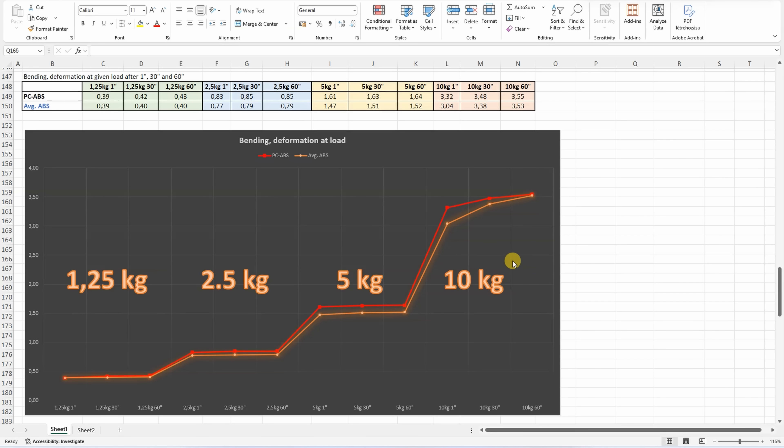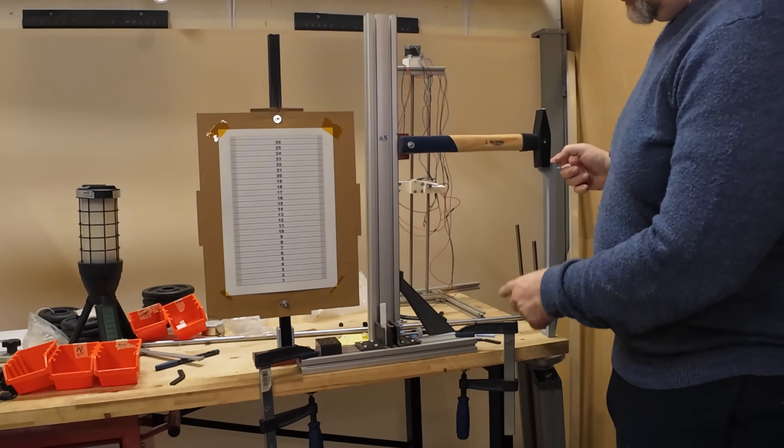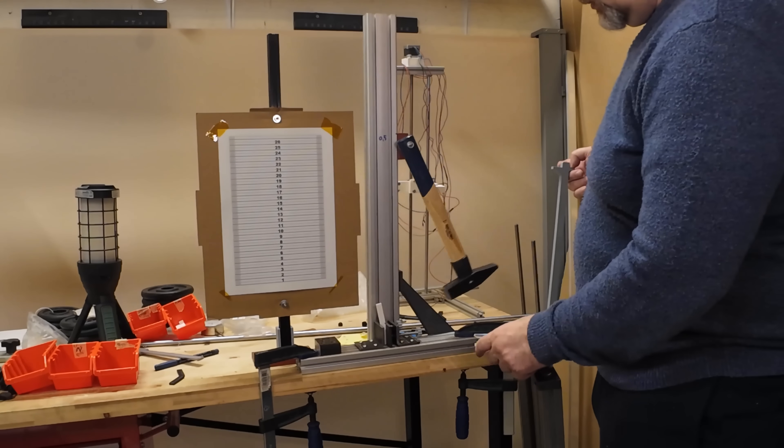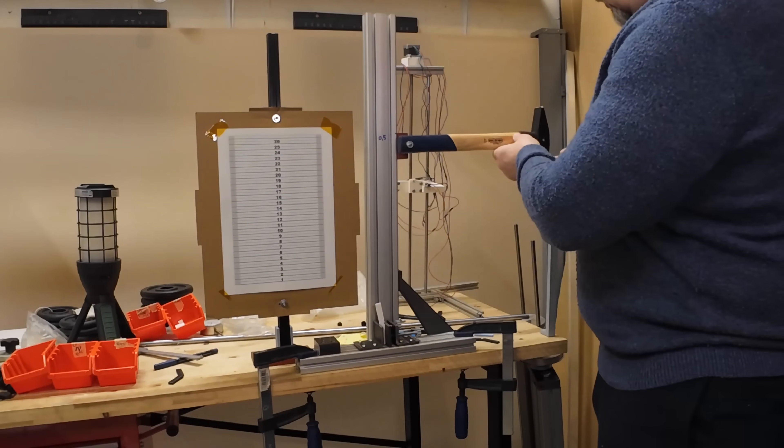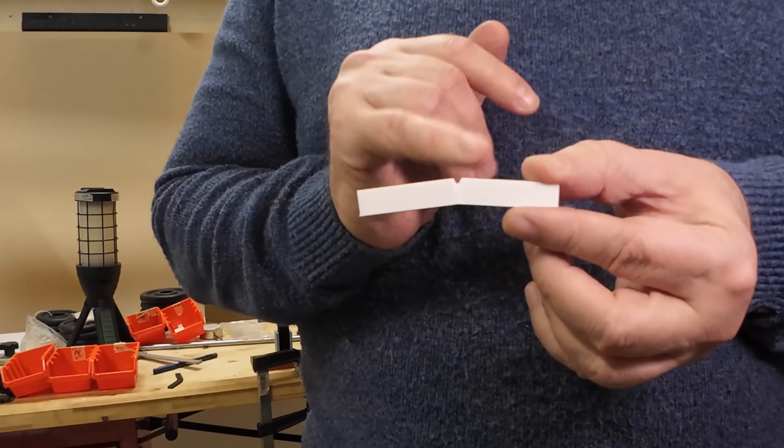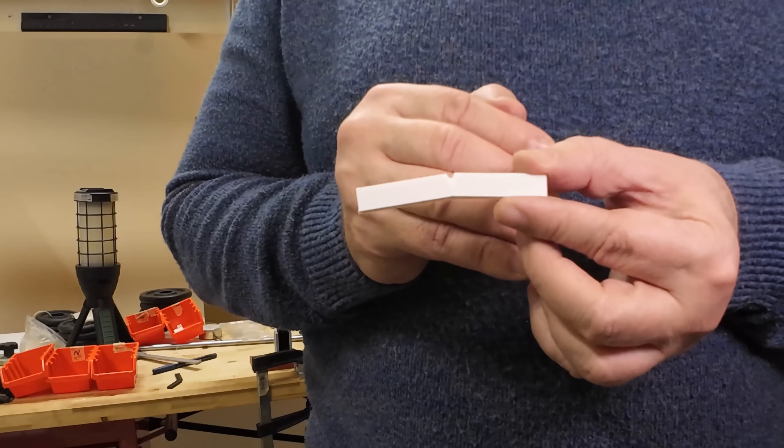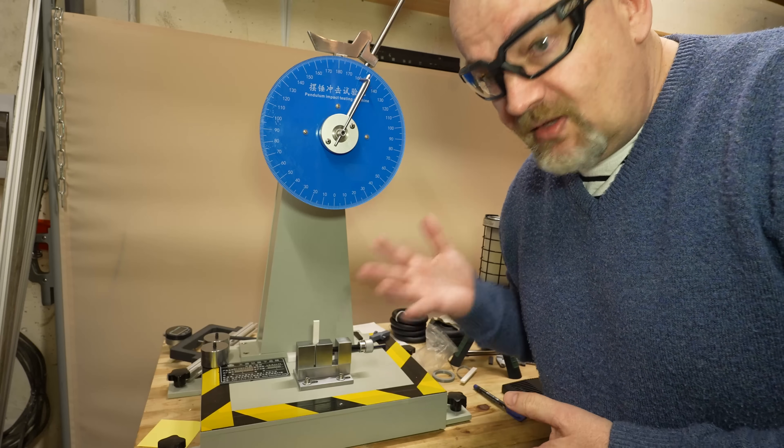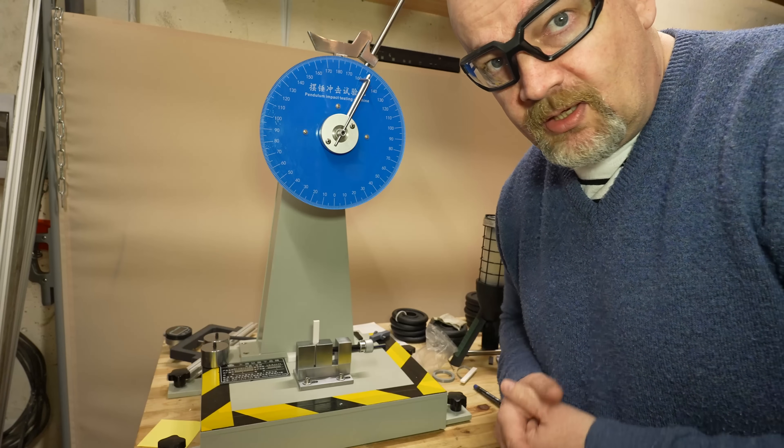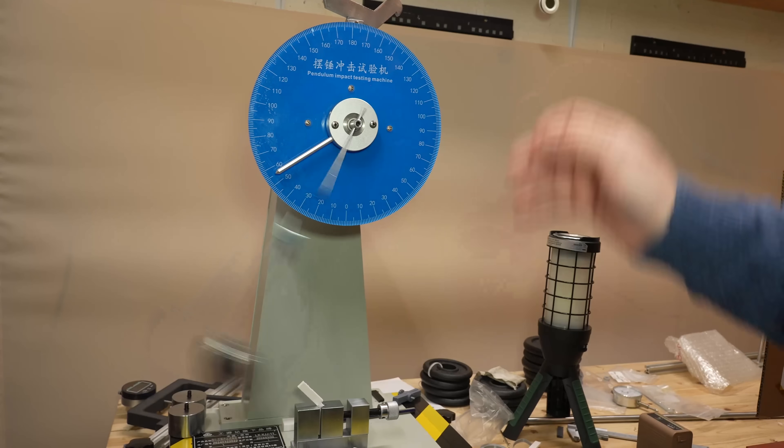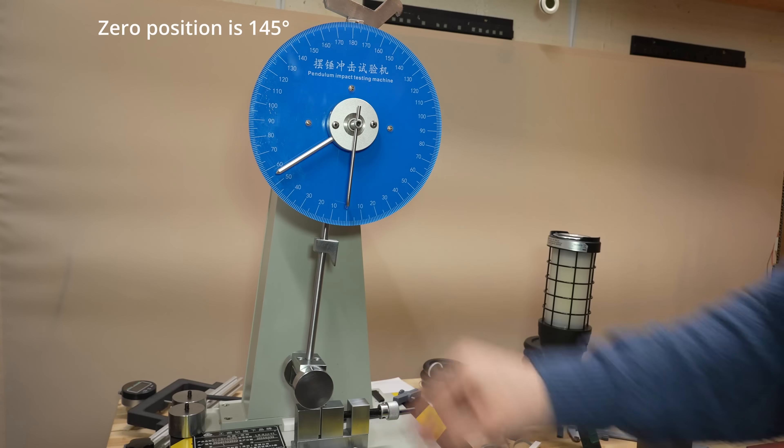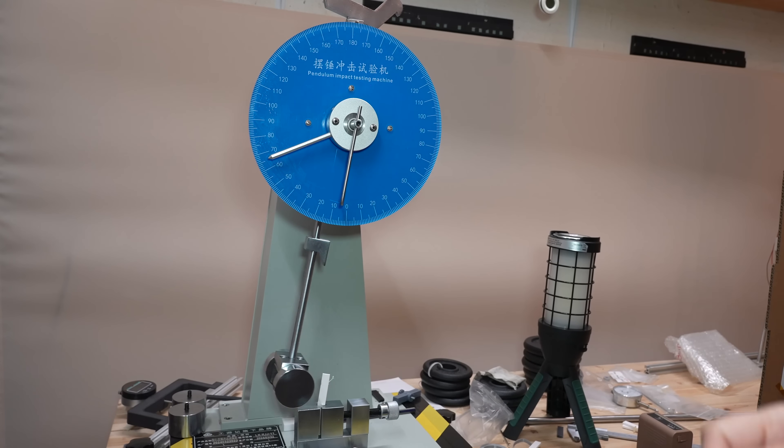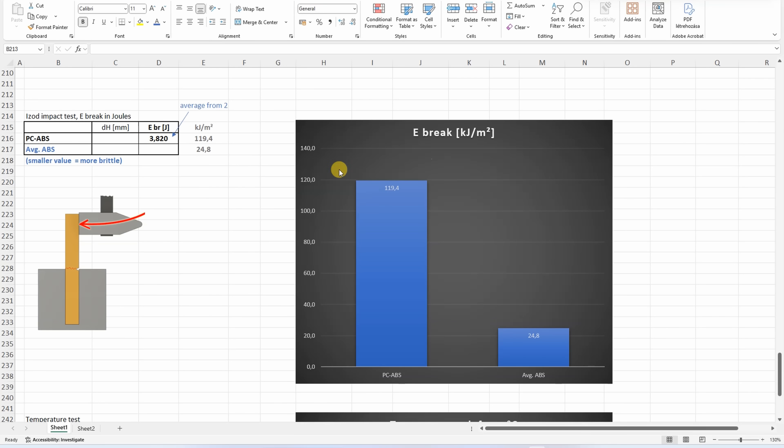Impact test with this half kilogram hammer. Sunlu PC ABS. Like every other PC ABS I tested so far, no brake under half kilogram hammer. I still want to have some measurable data, and this machine is good only for high impacts. That's exactly what I need here. 57. 66. This is very impact resistant filament, even compared to ABS which is considered as a tough material.